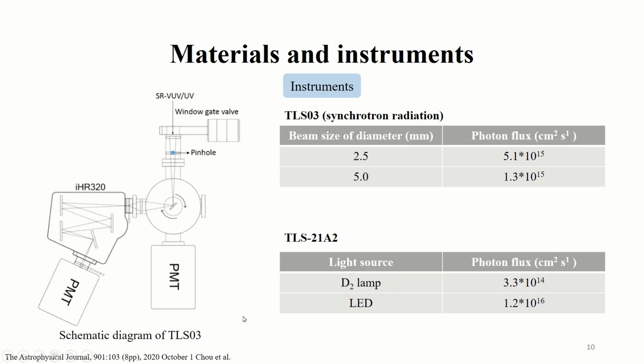This is a schematic diagram of TLS-03. PL and PLE experiments were performed at TLS-03. Synchrotron radiation comes from here to this chamber, hits the sample, and is detected by a PMT. Different beam sizes lead to different photon flux, and far UV treatment uses TLS-21. There are high dose and medium dose photon flux treatments. They will be discussed after the results and discussion.